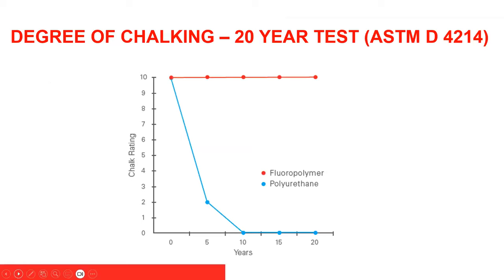So here's a real world example of chalking of a fluoropolymer versus a polyurethane. This was done offshore, off the shore of Japan, very high UV levels. And they would go in periodically offshore and take these panels and evaluate them for chalking. You can see over a 20-year period, the fluoropolymer hung steady at the 10, which is a very good rating, essentially no chalking at all, where the polyurethane, which is kind of a standard high-performance option, really degraded within the first 5 years, and within the first 10 was completely chalked out. So at that point, the top coat has been compromised way beyond the aesthetics of it, and is starting to attack the undercoats that are really there to help protect the substrate.